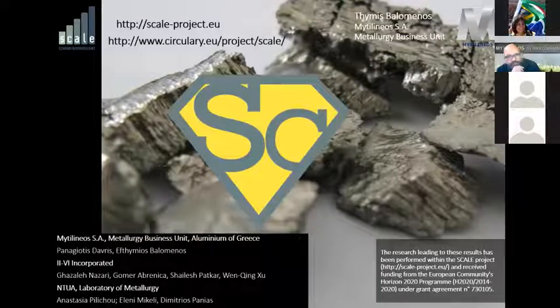So we will keep working on it and see if it makes sense. On a first level, it does seem to be not so practical unless you do an even more complicated flow sheet where, for example, you take out alumina first from the slag and then you take out the scandium. But the more steps you add, the more difficult this becomes to realize, right? Because industry is not looking for building 5 new plants. It's looking for simple ideas that they can put onto their plant. Okay. All right. No questions from me.